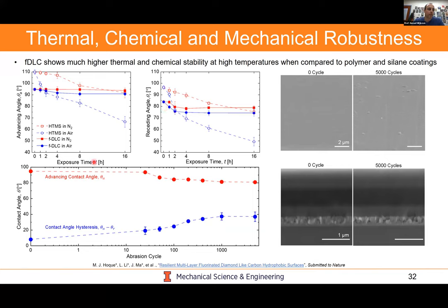Now, we have a Taber tester and we could do mechanical abrasion of the interface. What you're seeing here is that for up to 5,000 mechanical abrasion cycles using a diamond tip, we could still maintain stability for dropwise condensation. So what you're seeing here is an SEM of zero cycle, an SEM of 5,000 cycles. And on the bottom here are focused ion beam cross sections of the coating at zero cycle and 5,000 cycles. And it's indistinguishable, meaning that the coating is very adherent, it's very adhered, and it lasts for quite a long time.